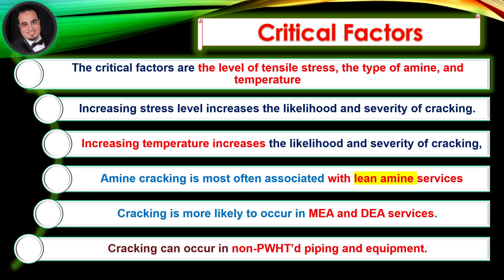The critical factors are the level of tensile stress, the type of amine, and temperature. Increasing stress level increases the likelihood and severity of cracking. However, cracking has been reported down to ambient temperatures with some amines — monoethanolamine in particular.